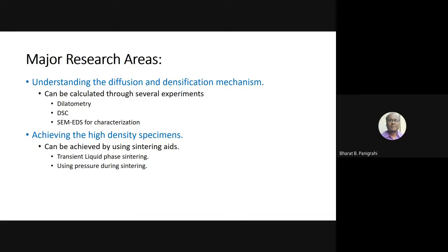Then how to achieve a high density. For making a component, you need to achieve a high density. There are different ways we try to evolve. Not all powders are good in sintering. Let me be honest, you need to really optimize the process. You find ways by which you can enhance the densification. Enhanced densification means how you can reduce the porosity or defects inside the component, so that mechanical properties can be better and better. So that is one aspect, purely on how to enhance the densification, which can be done through solid state sintering as well as liquid state sintering. So we also employ both techniques, solid state as well as liquid phase sintering, to get a much denser microstructure.